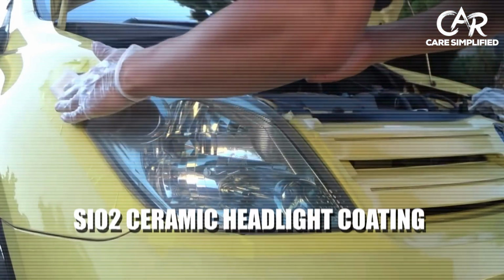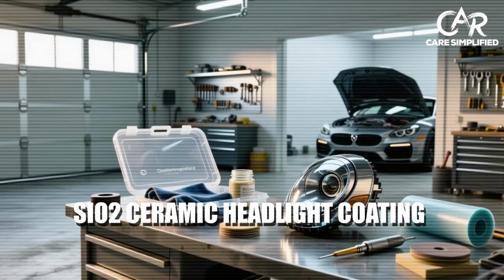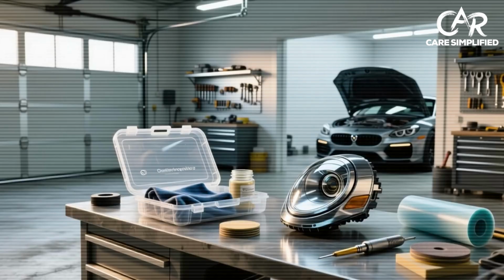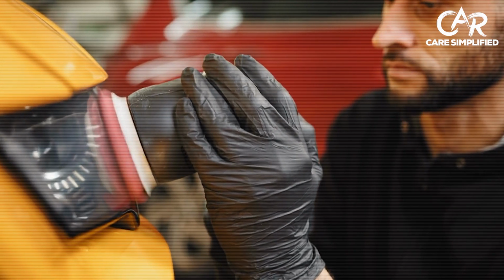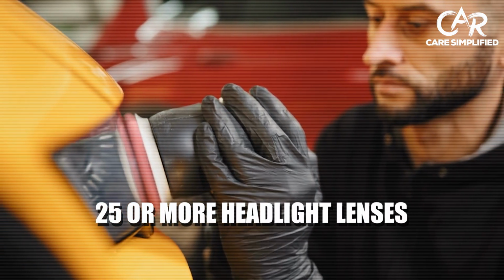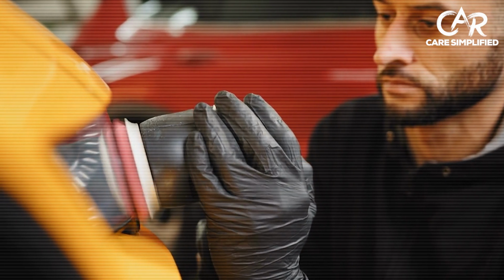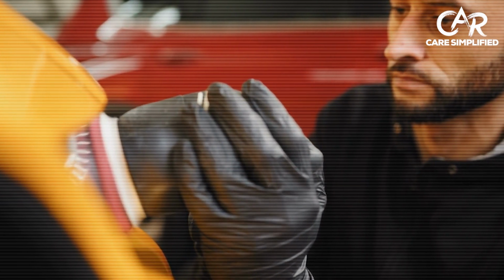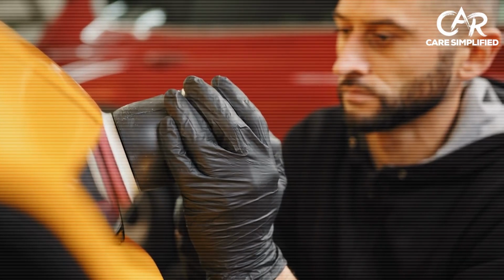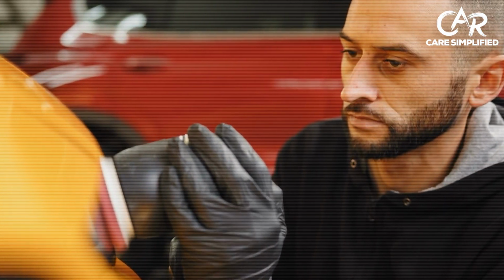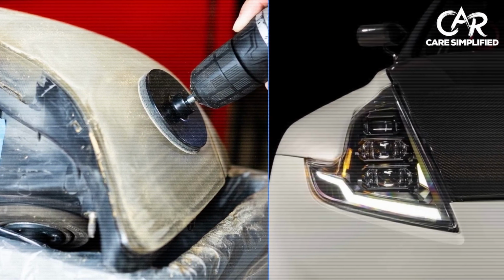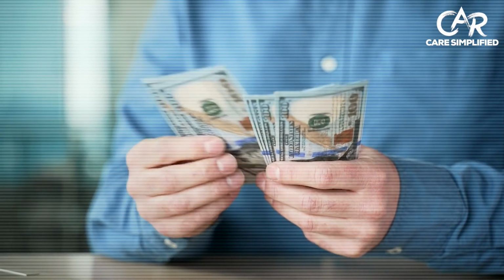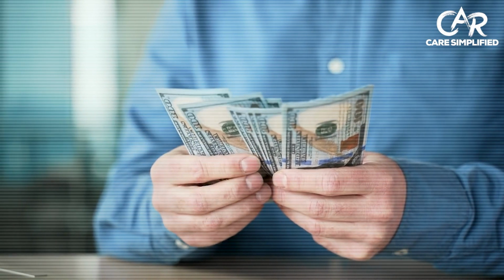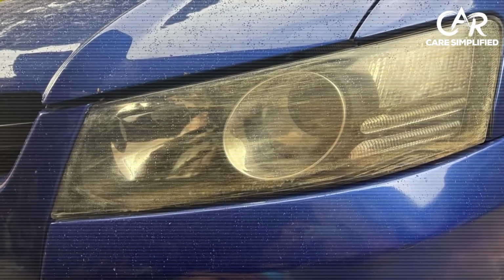A single bottle of SiO2 ceramic headlight coating costs between $20 and $40 and contains enough product to coat 25 or more headlight lenses. Apply it to a new vehicle and reapply a thin maintenance coat every 1 to 2 years at a cost of roughly $5 to $10 per application because you use so little product each time. Over an 8-year ownership period, your total investment in headlight protection comes to approximately $40 to $80. Compare that to the alternative. Without preventive coating, your headlights degrade by year 3 to 5.